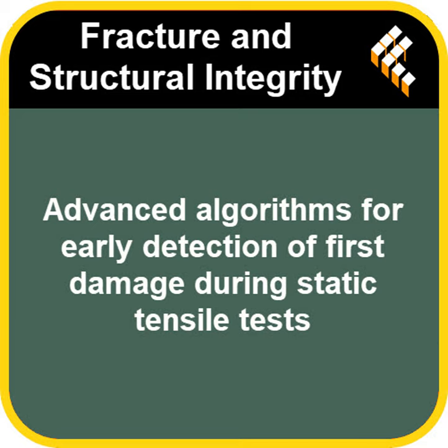Okay, interesting. Now, the DeAndrea paper we're looking at focuses on an even more efficient approach, right? The Static Thermographic Method, or STM. What makes STM such a big step forward? Yes, STM. Proposed by Risitano and Risitano back in 2013. It's really exciting because it lets us get a design parameter linked to that fatigue limit super fast. And it does this by analyzing the energy release during just a single monotonic quasi-static tensile test. Okay, monotonic, quasi-static. So, just one slow, continuous pull on the material, not the back and forth cycling. Exactly. No repeated stress cycles needed.